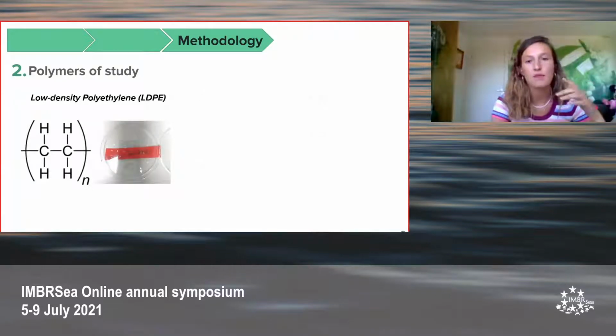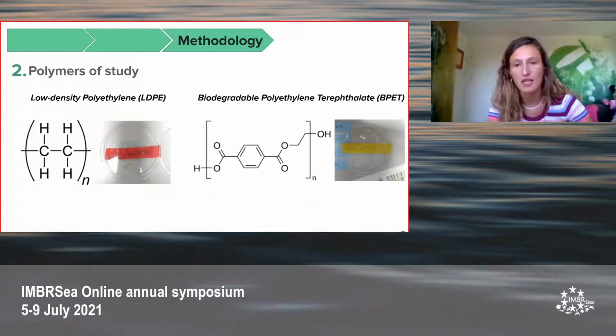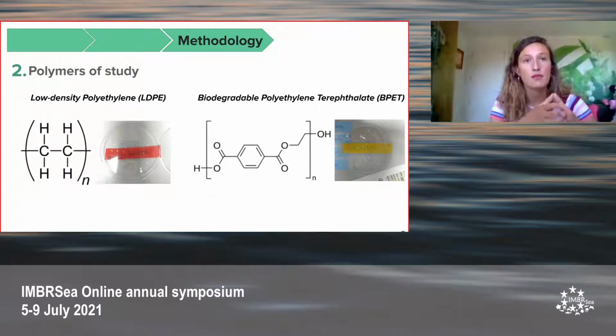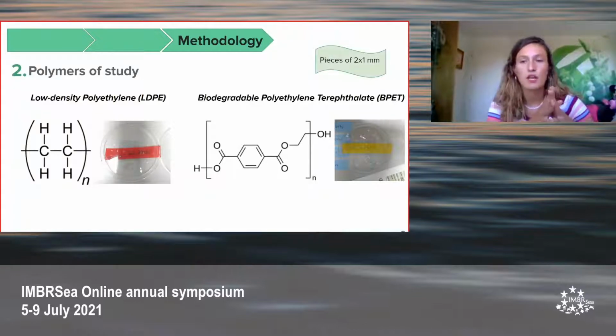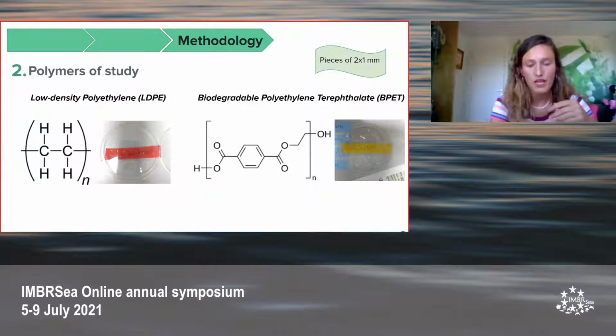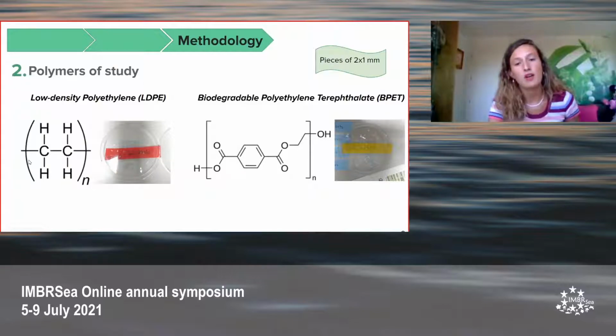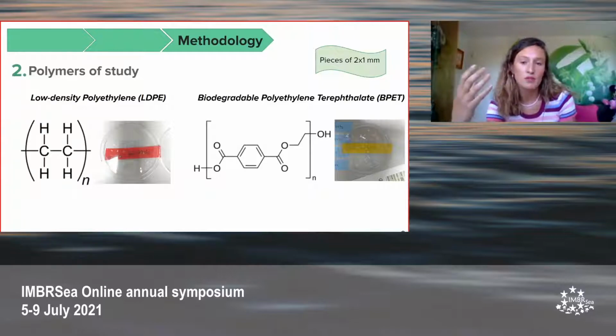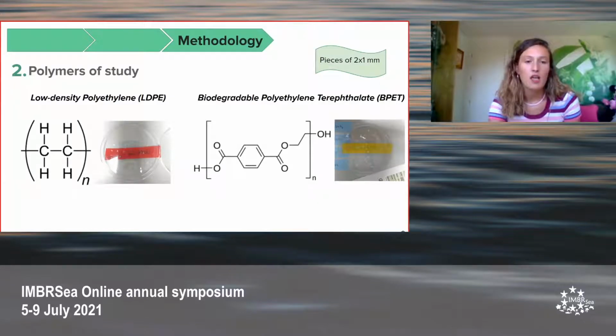As I've been previously mentioning, our two polymers of the study were the low-density polyethylene and the biodegradable polyethylene terephthalate. They both come from commercially available plastic bags, from which pieces of 2 times 1 millimeter were cut. Here we can see the molecular structure of both polymers, which is really important for this study, as polymer degradation depends on the number of carbons present in the molecule and the structural arrangement of it.